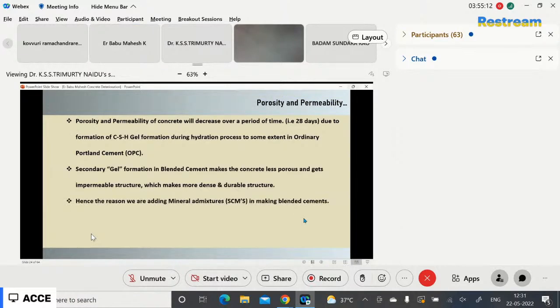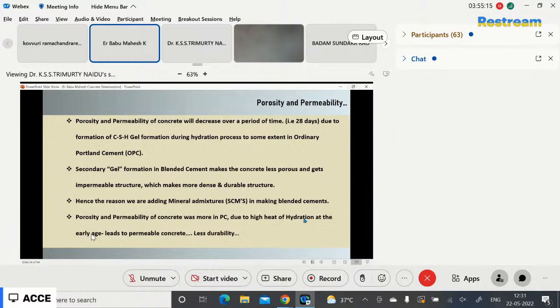The additional C-S-H gel in this system helps in pore refinement in the cement paste and makes the concrete more impermeable than the Portland cement paste system. The porosity and permeability of the concrete will decrease over a period of time, that is 28 days, due to formation of C-S-H gel during the hydration process to some extent in ordinary Portland cement. In blended cement, the secondary gel reaction makes the concrete less porous and gives an impermeable structure, which makes a more dense and durable structure.